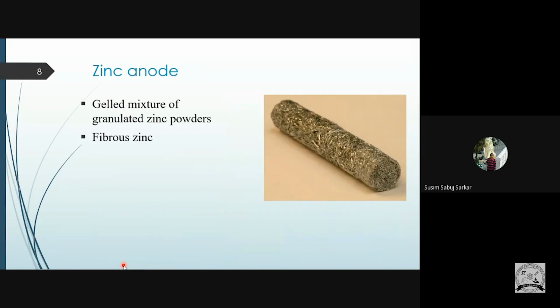Okay, so what is the first thing? The zinc anode. Zinc anodes are a gelled mixture of granulated zinc powder. This is one option, and another is fibrous zinc. This is the image of fibrous zinc. Why fibrous zinc? Because the surface area of fibrous zinc is more than the other. Previously, people used the gelled mixture of granulated zinc powder because small zinc granules have more surface area, so they are more reactive and we can produce more energy. Later, people tried fibrous zinc, using very thin fibers of zinc, whose surface area is greater, so the reactivity of our zinc is higher, and ultimately we can produce more energy.